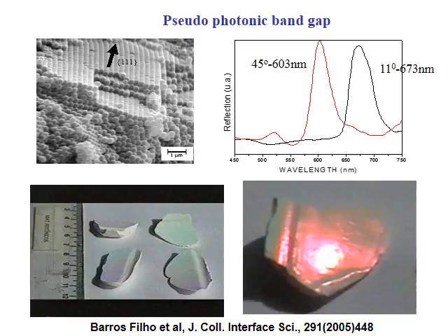This is not the case for this material. The photonic band gap for red color appears in just one direction. We say that this is a pseudo band gap. The plot shows reflection spectra obtained at different angles of observation. The peak corresponds to diffraction. We can conclude that since there is a shift as a function of the angle, obeying therefore the Bragg law of diffraction.